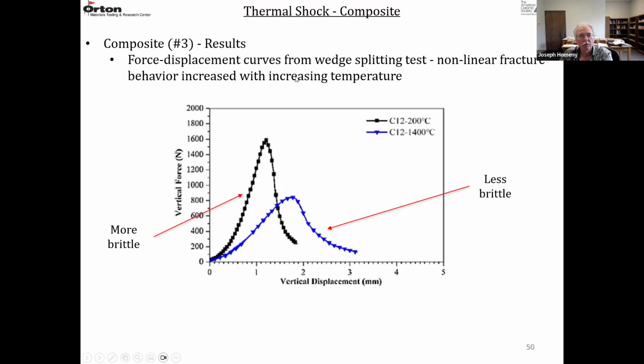This is the force displacement curve, a typical curve for these materials. This is C12. The black curve here is C12 at 200. The blue curve is C12 at 1400. So as you go up in temperature, the strength decreases, but the material becomes less brittle, more ductile, and the areas under these curves start to increase. So the nonlinear fracture behavior increased with increasing temperature.